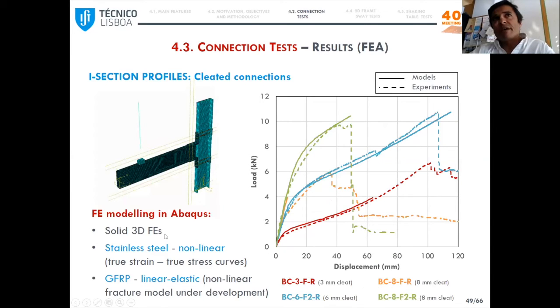So we also did some FEA of these connection tests. This is just an example of the simulation of these I section profiles with cleated connections. We used Abaqus. So stainless steel was modeled as nonlinear, and for now, GFRP was modeled as linear elastic. You can see that the response was quite accurately predicted, but failure in the GFRP material is still pending on the development of fracture models that are ongoing in our group.